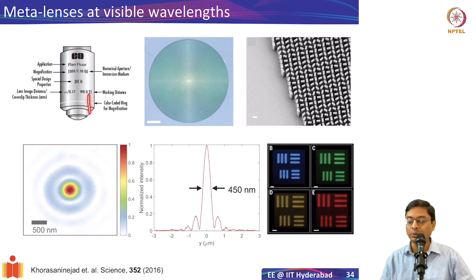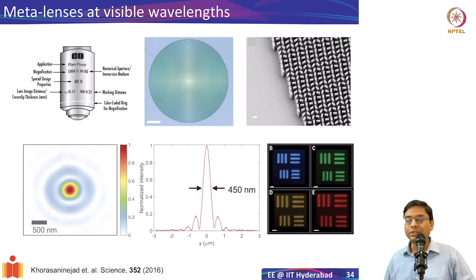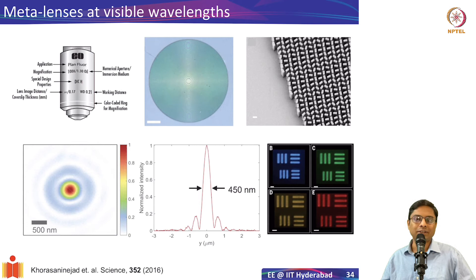This work from Professor Capasso's group at Harvard showed that with these dielectric structures you can create a focused beam comparable to standard objectives. The metalens height is on the order of a wavelength, compared to two to three inches for a conventional objective. They demonstrated lenses operating over visible wavelengths — blue, green, and red — and clearly resolved a standard resolution target. There is great interest in this for AR and virtual reality applications.